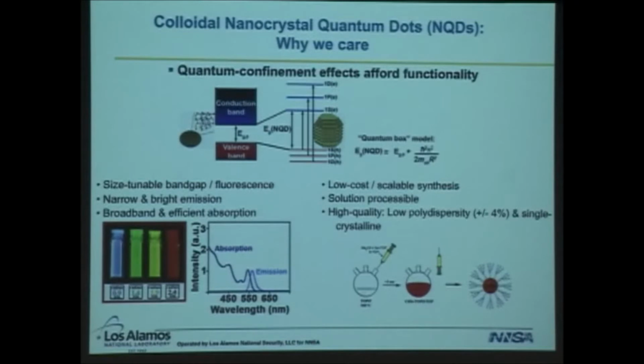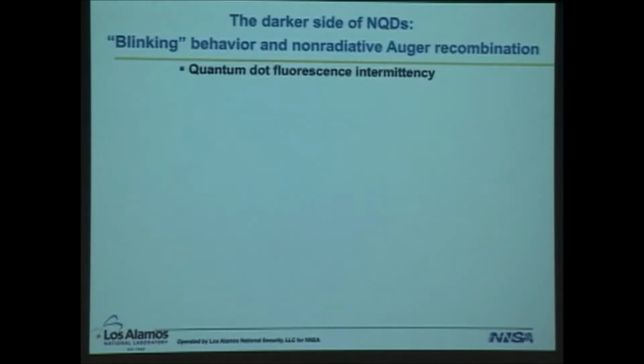I just want to point out, it becomes somewhat important a little bit later in terms of device applications, that all these materials that are grown in the flask comprise not just the inorganic core part, but also a monolayer of organic ligands that enables these particles to be suspended in solution for long periods of time and to be readily processed. But it also can cause problems, as we shall see.